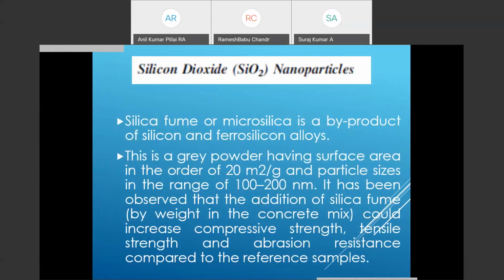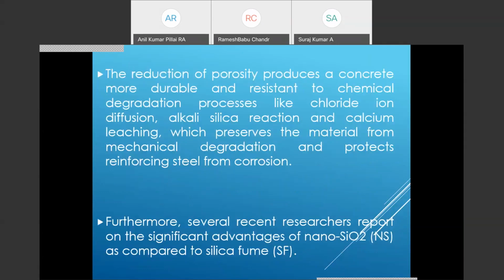Here again, it talks about silica fume or microsilica, the byproduct of silicon and ferrosilicon alloys. It has a huge surface area, 20 square meters per gram. Imagine the surface area is 20 square meters per gram, and the particle size is in the range of 100 to 200 nanometers. It has been observed that addition of silica fume could increase compressive strength, tensile strength, and abrasion resistance compared to reference samples. Lower porosity produces a concrete more durable and resistant to chemical degradation processes like chloride ion diffusion, alkali silica reaction, and calcium leaching.